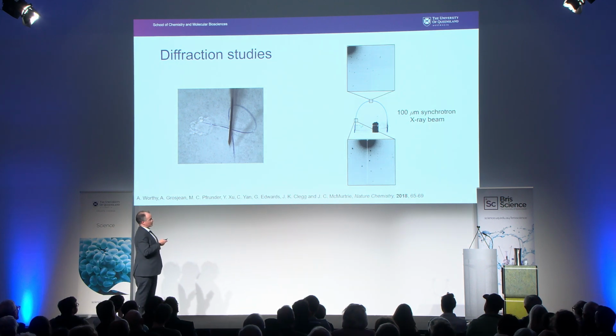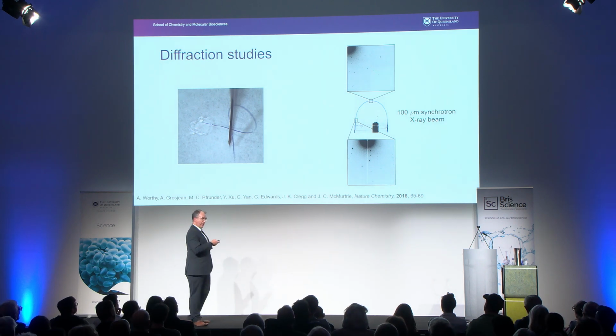In the straight part of the crystal here, where it's not really bent, the crystal isn't under any strain, the diffraction pattern is beautifully sharp. But where it's bent, the diffraction pattern is now again very broad. So we're seeing a change in the crystal structure, a change in our diffraction pattern, from applying our strain to the crystal.